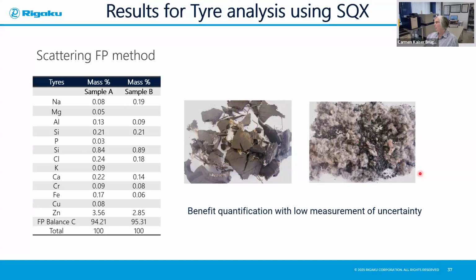And now we can comfortably make what we call a pressed powder from this. Of course, the pressed powder needs to have a defined density, so we need to have an infinitely thick sample to be able to measure all the elements that you see here. In this example, you can see that the carbon portion was measured using the fundamental parameters scattering FP method. This means we measured the Compton line to get the balance of the material, which is in this case from a sample A and B. We measured it twice and prepared it twice. You can see there are differences because it's heterogeneous.